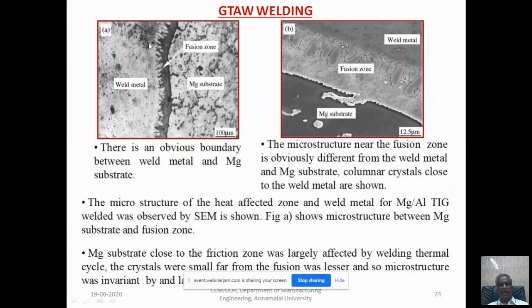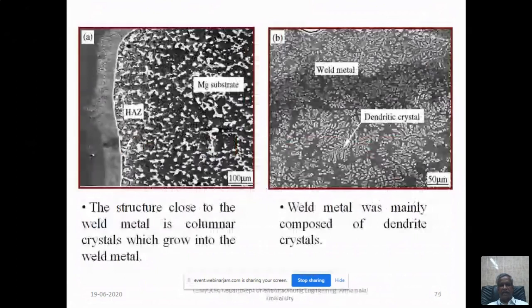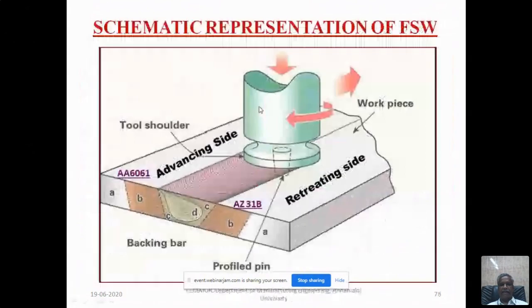As I told you, aluminum alloys are FCC and magnesium alloys are HCP metals. They will not mix together. And this is the larger spectrum of the microstructure of the interface, the intermetallic layers. And here we did it using FSW. On the advancing side we used 6061, and on the retreating side we used the magnesium alloy.